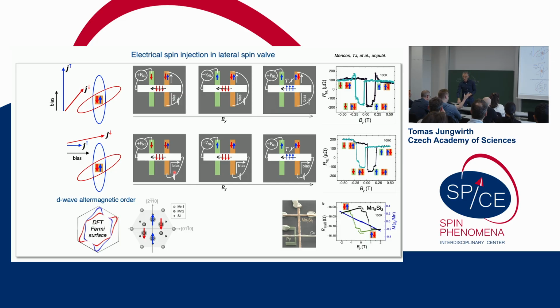Right, but could you exclude the fact that your interfacial structure itself prefers a particular spin sublattice at the interface, in which case you would have preferential spin injection for one spin, but not due to the band structure, just due to the interfacial structure?